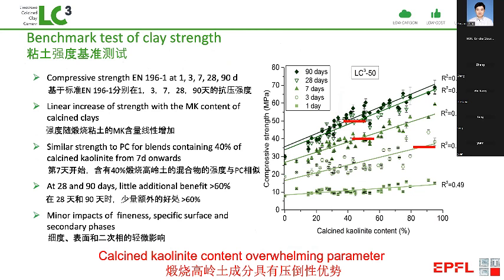So the other minerals which are present, like quartz or iron oxide, do not influence the results at all. It's just the presence of the kaolin. And the red lines here indicate the reference strength of the Portland cement. So we can see that at 7 and 28 days, we only need about 40% kaolin content. And some of these clays, even with 30%, are really doing very well.